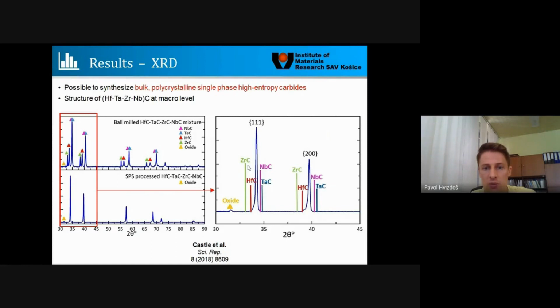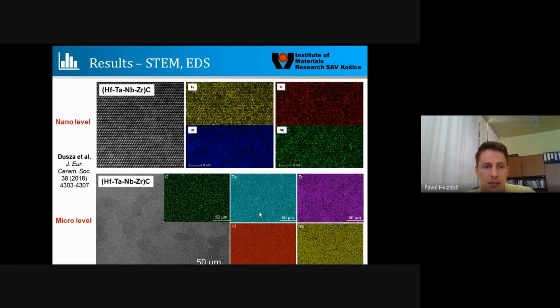And the peaks, as you can see, fall between the individual peaks. On the right side, you can see those lines, but those lines are really just for visualization purposes, where the individual monocarbide peaks should be present, but they are not there. We can see only one peak, which corresponds to this hafnium, tantalum, zirconium, niobium carbide structure. So this confirmed that it was possible to synthesize a single phase material, and it showed real atomic randomness at different levels. At the nanoatomic level, you can see that the individual atoms are distributed randomly. And of course, also at the micro level, when we observe several grains, we could say the same.